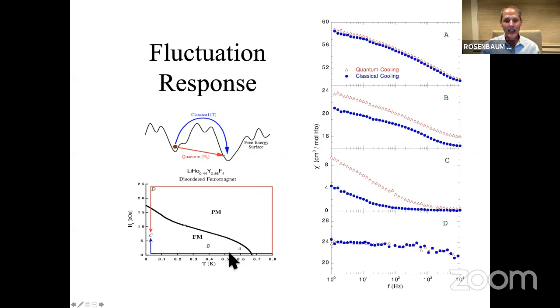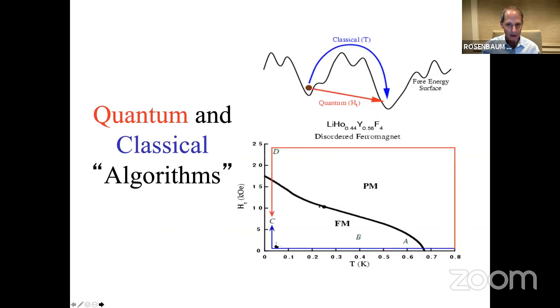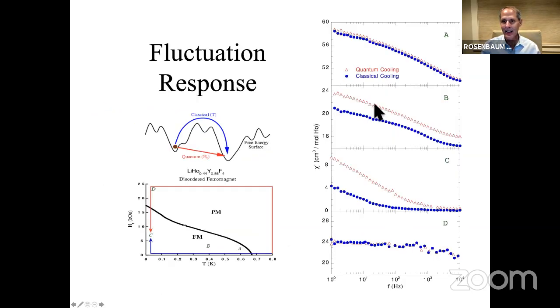As I go a little deeper into the state, I start seeing a difference between the quantum in red and the classical, but not much. They look basically the same. As I go deep into the ferromagnetic state, the two curves start separating, and the onset of the response to this AC magnetic field starts occurring at much higher frequencies. And this is the quantum speed up. I'll talk about that in a second.